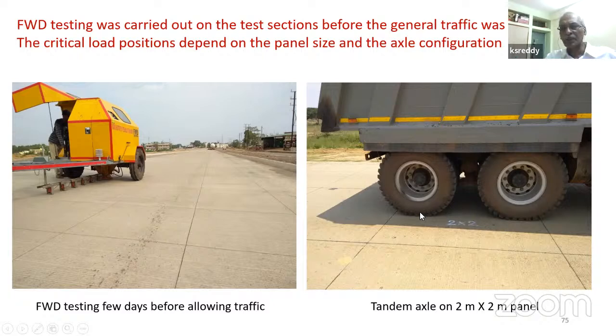For example, as you can see, if you've got a 2 meter by 2 meter panel size and a dual tandem axle, the front axle placed close to this edge and the rear axle placed close to the edge could be a critical load combination for producing a transverse crack in this direction. Similarly, as the panel size varies from 1 meter by 1 meter to 2 meter by 2 meter, there could be several combinations of load position. Just the dual wheel itself could be a problem. Tandem axles could be a critical position. So we identified several critical positions which can produce longitudinal cracking as well as transverse cracking.